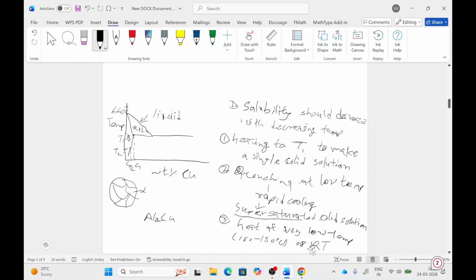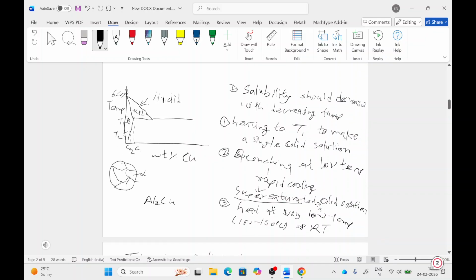When we keep the material for a long period at low temperature or room temperature, small precipitate particles will form in the grains and at the grain boundary also. So these tiny particles form with time in the aluminum copper system, and they interact with dislocations, increasing the strength of the material.